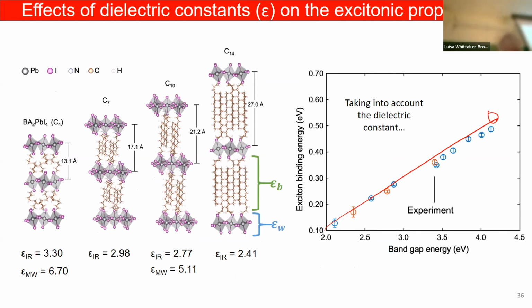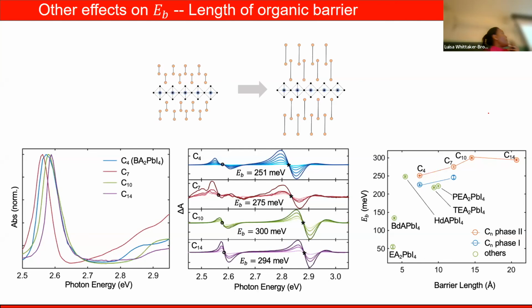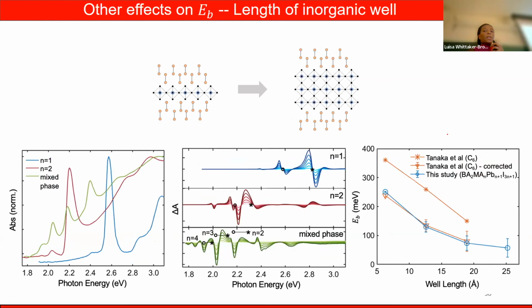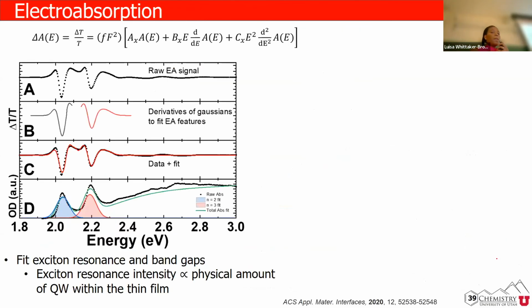All right, so then with that, we look at how the organic barrier changes the exciton binding energy. When we increase the organic length, we kind of plateau because they don't feel each other that much. So there's a lot of screening of the exciton, right? So the binding energy doesn't change that much. Then when we change the inorganic layer, again, as you increase the number of inorganic structures, it resembles more of the 3D. So the exciton binding energy decreases towards free carriers, okay?